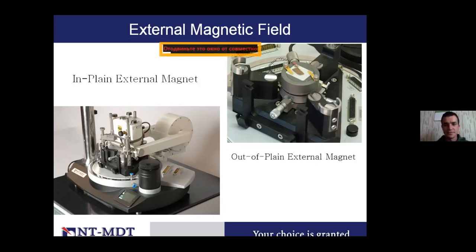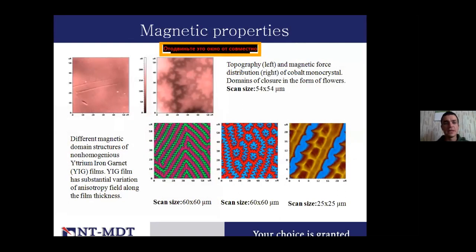And here are some examples of different samples which show you differences in magnetic field. So a yttrium iron garnet film, for example, on the bottom, or cobalt monocrystals on the top. On the top, for example, from the left, you can see the topography, and on the right, you can see the same area obtained at the same time, but which shows us the magnetic field distribution, similar to the images on the bottom.